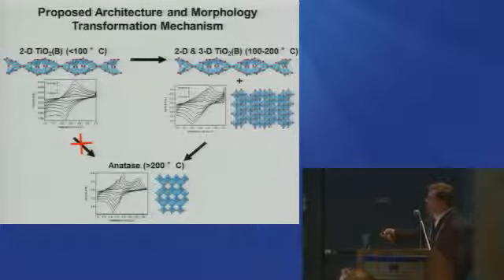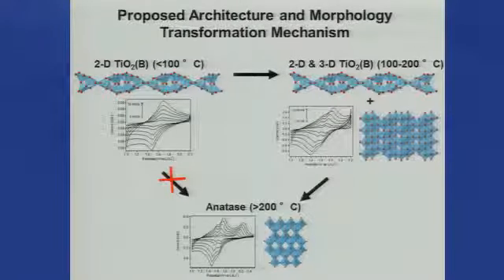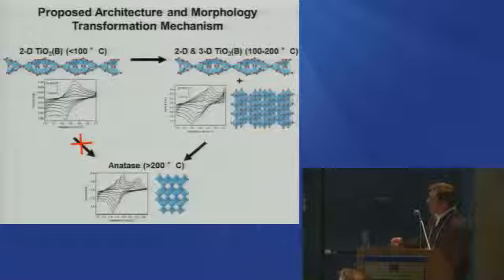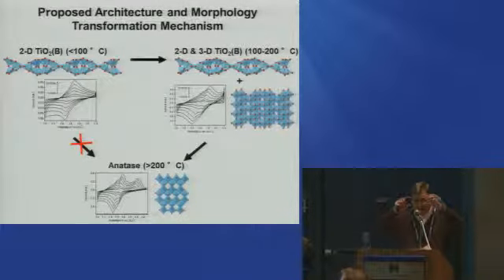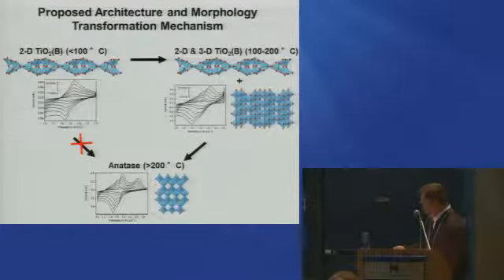But to summarize, the reason why you can get such high lithiation has to do with the fact that this is all surface. And so this is what we consider a redox pseudocapacitive mechanism, where all of the lithium ions are stored right at the surface. In anatase, when you form that phase, it actually looks much more diffusional based on the scan rate dependence. And these other 2 peaks that grow in for the nanoparticle geometry have to do with the change in the filling of the number of sites and the energetic dependence on that. In particular, when you make a nanosheet, you get compression along one axis, and that makes the C site more stable for lithiation, and that actually lithiates first relative to the other sites in this particular structure.